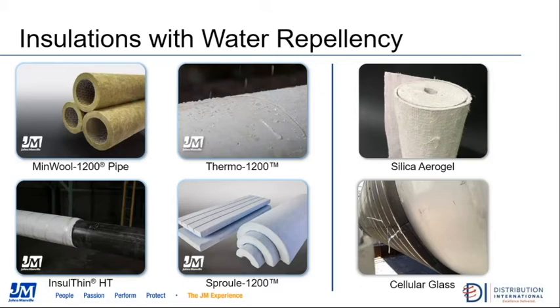Some examples of different insulation materials that do offer water repellent or hydrophobic properties include Johns Manville mineral wool 1200 pipe insulation. That does have an integral water repellent treatment. Johns Manville's Thermo 1200 calcium silicate is water repellent as well, designed to help give the contractors installing the material extra time to get it jacketed, even if there's a pop-up thunderstorm, without risk of the material getting damaged due to absorption of rain. Johns Manville's Insul-Thin HT microporous thin blanket insulation is treated with a hydrophobe so that it does have hydrophobic properties. And the Sproule-1200 expanded perlite material is also a hydrophobic material.